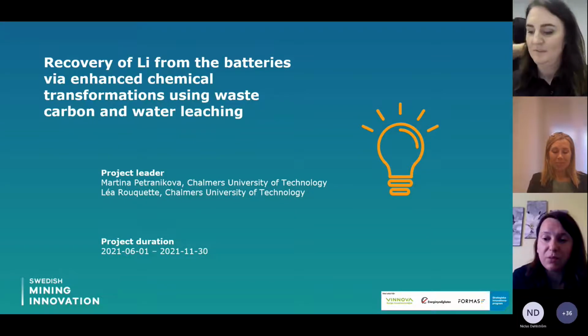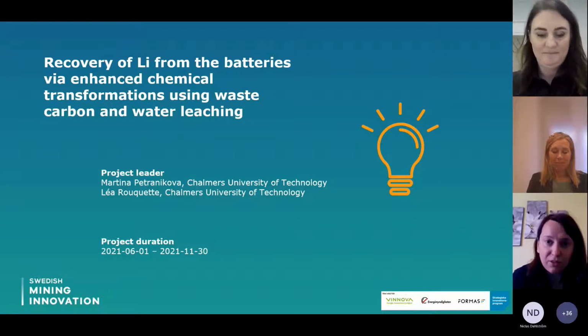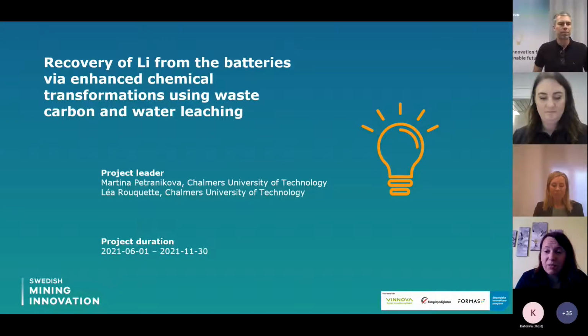So our idea was to recover the lithium after the thermal pretreatment, because this is usually used for battery recycling, just with water leaching. What we did, we tested pyrolysis and incineration, and we tried to see the addition of graphite, and carbon, which is already present in the batteries, either in the form of graphite or in the form of the organic components or the separator, which is polypropylene.